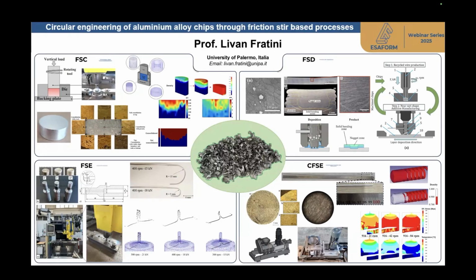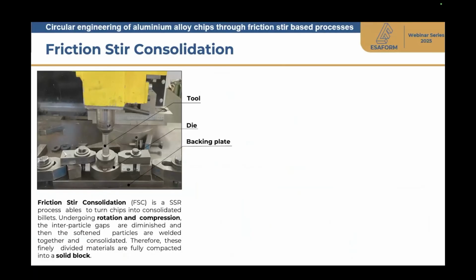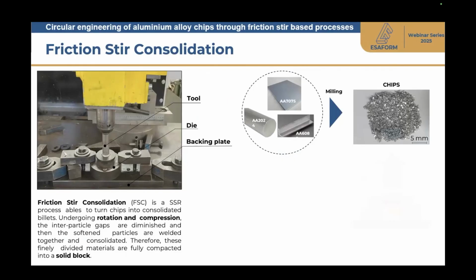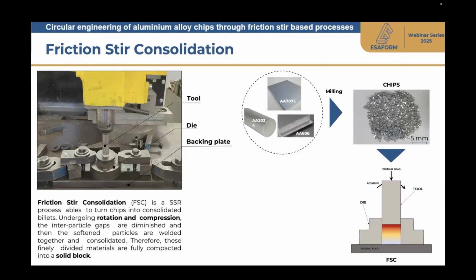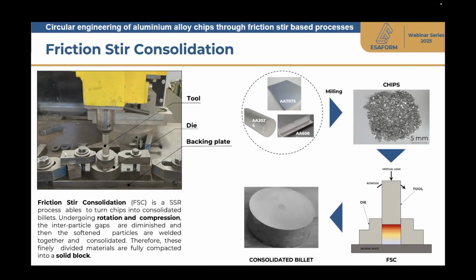Well, as we start with friction stir consolidation, we have to observe that starting from chips, the idea in this process is to put the chips into a chamber, a die, a closed chamber, and to use a vertical tool, a vertical movement tool with a vertical load applied and put in rotation together in order to press the chips and to activate the solid bonding operation. So we have rotation and compression. So we have the tool rotation speed and compression force as process parameters together with the time. And in this way, as the process is carried out, a proper consolidated billet can be obtained under certain conditions, of course. This is a very simple process, but very effective with, of course, some limits.